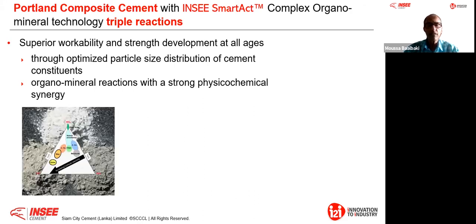Therefore, in this ternary or quaternary system, we can optimize the particle size distribution. Of course, this would be very difficult if I called our company in Thailand and told them, please send me your composite cement. This is difficult. But if we do it ourselves in Sri Lanka, we can do it. Therefore, we can optimize the particle size distribution. That is very important because the grindability of clinker, slag, fly ash and limestone is different. This gives us the opportunity to optimize the packing density.